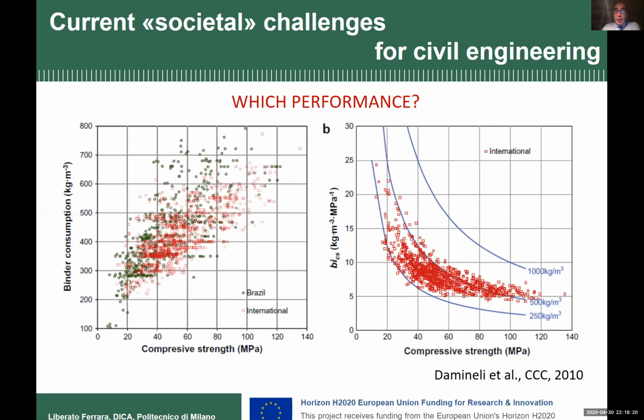We have also become very good at exploiting at best the strength capacity of our binders. You can see on the right graph, to produce a 100 megapascal concrete, the effectiveness of the binder is such that we need 5 kilos per cubic meter per megapascal of strength of binder in the mixture, whereas to produce a 20 megapascal concrete, we use between 10 and 15 kilos. So these high strength mixes contain more cement, more binder, but it's also true that they use the binder 2, even 3 times better than in ordinary concrete.